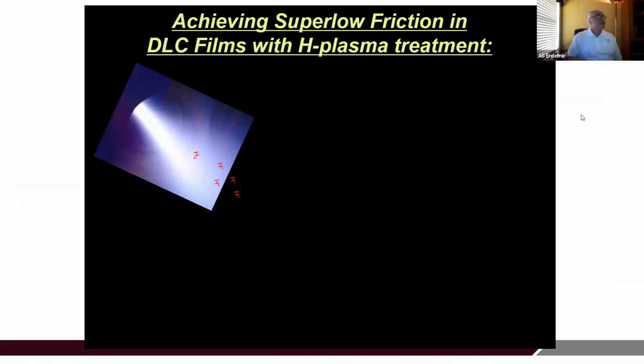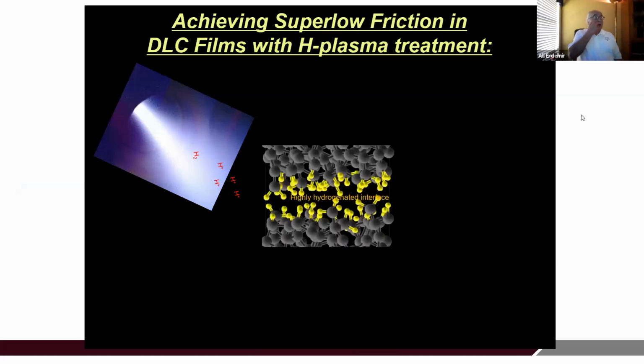As shown in these 3D TOF-SIMS maps. So to further prove our point, what we did was start with a hydrogen-free DLC. These are the kind of DLCs that you can directly sputter out of a carbon target in the absence of hydrogen, and these are mostly sp2 or sp3 bonded carbon, but on the surface you may have some adsorbed species, and that's about it.